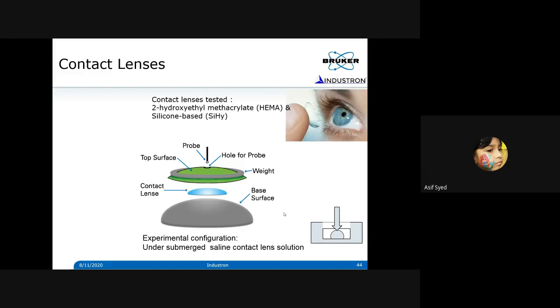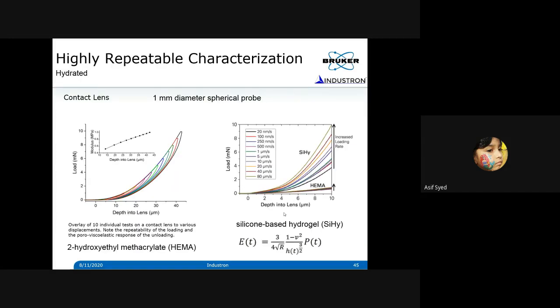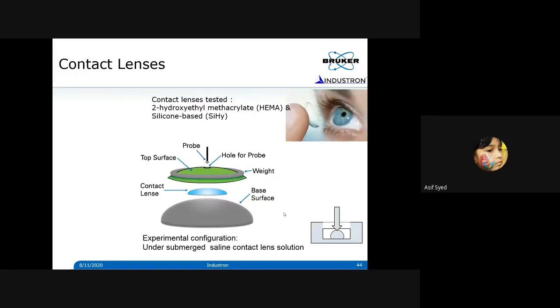So when we dealt with Johnson & Johnson, who was interested in developing a technique to measure the properties of contact lens, we collaborated with them, and we were able to develop a technique where you can measure the properties of this hydrogel using nanoindentation, the depth sensing indentation technique. So we developed some kind of fixtures and jigs so we can put this lens in a conformed way inside a solution and bring a probe and make contact and make a measurement. Okay. So I will be showing some of these commercially available contact lenses and how we measure the properties using this BioSoft instrument.